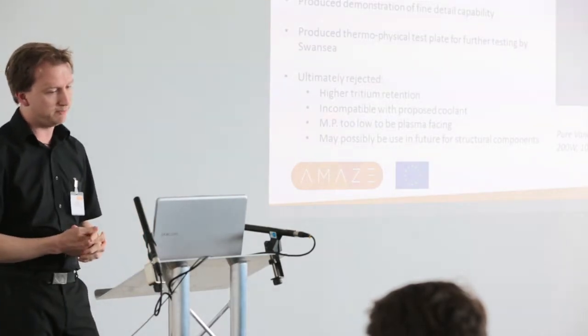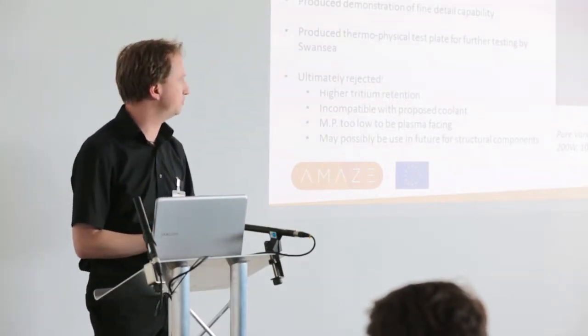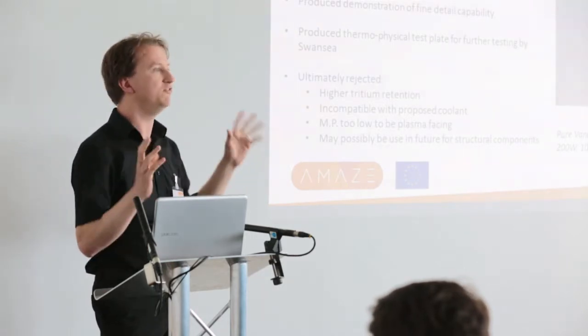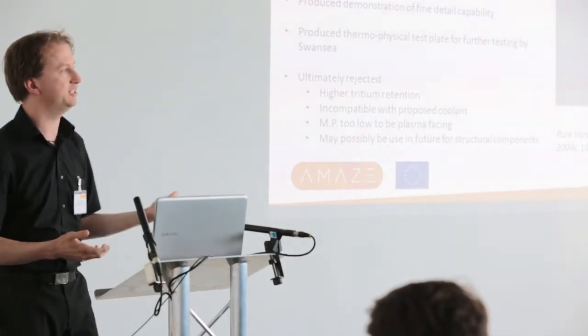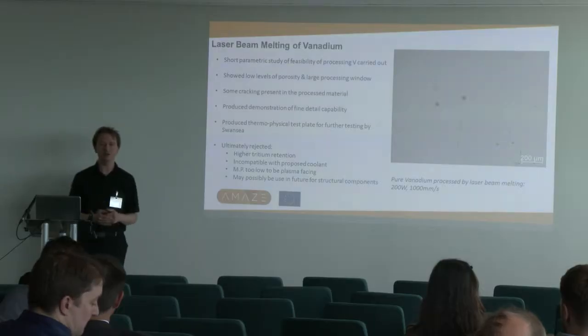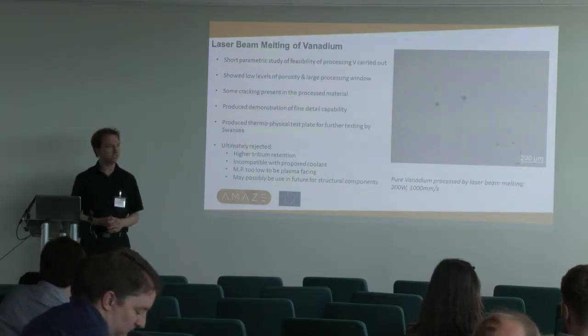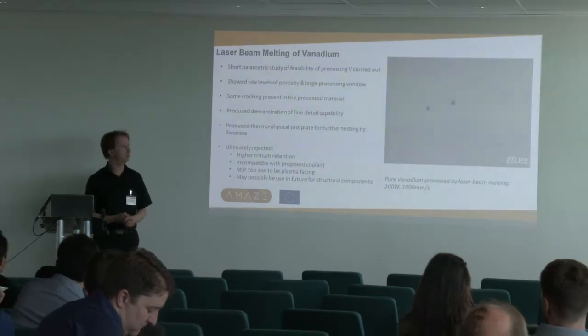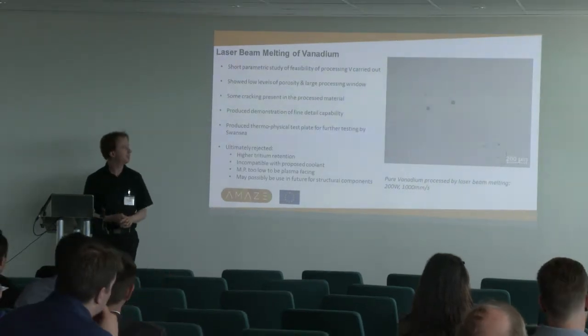But it was quite nice, and as part of this work, we produced a thermophysical test plate for CCFE. We're going to run a whole load of tests and hopefully get a nice little publication out of that in the near future, because it's quite novel. I don't think many other people have processed vanadium by laser powder bed.